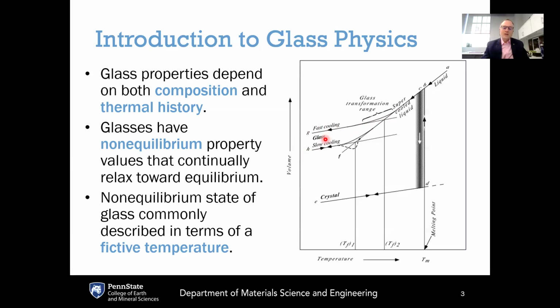Glass has some properties that are like a solid, like the mechanical response of a glass, but the structure of the glass is a liquid-like structure because it comes from freezing in the structure of a supercooled liquid. So glass has some properties that are like a liquid, it has some properties that are like a solid, but it has its own unique properties as well because it has fallen out of equilibrium with respect to the supercooled liquid, which in turn is only metastable compared to the true equilibrium, which is the crystal.